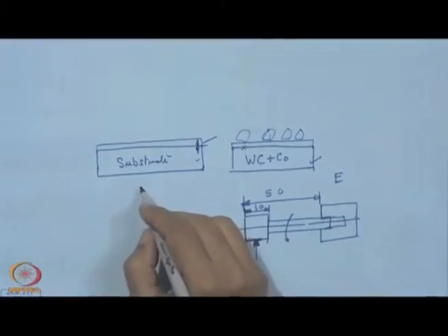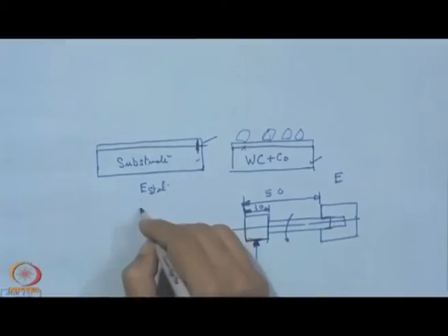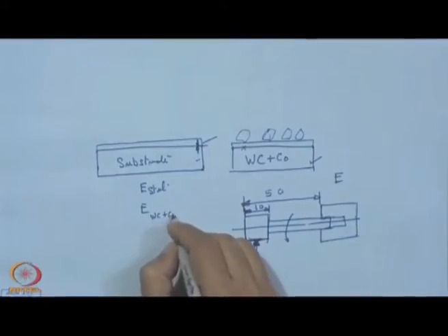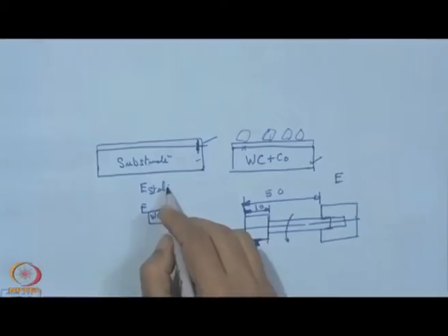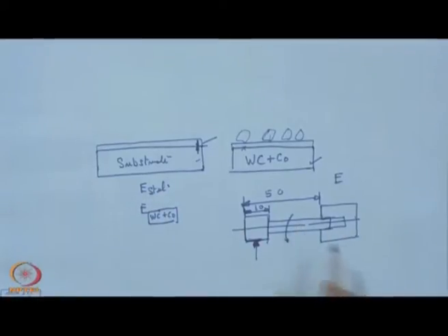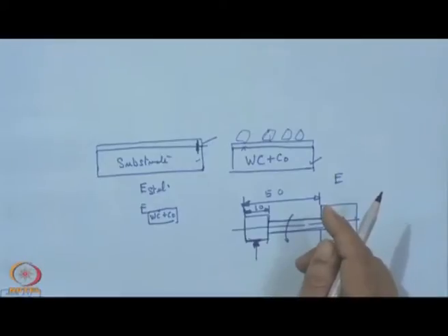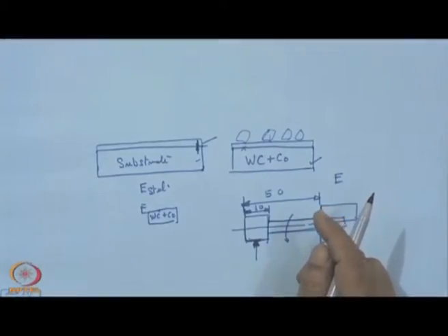So, if we consider the E value of steel and the E value of this tungsten carbide cobalt, it will be at least 3 times that of steel. So, under the same level of force, if we have a tungsten carbide cobalt matrix shaft and a normal steel shaft, then with the same level of grinding force, we expect 1/3 of the deflection, and definitely that will be a good contributor in holding the precision or accuracy of the tolerance or dimension of the piece being ground or processed by this abrasive tool.